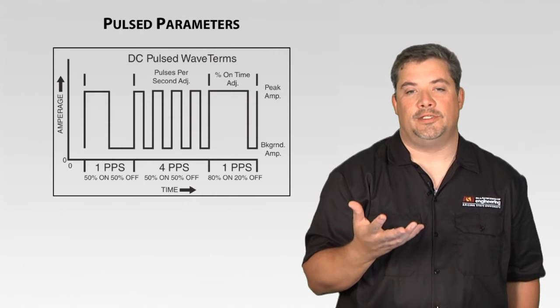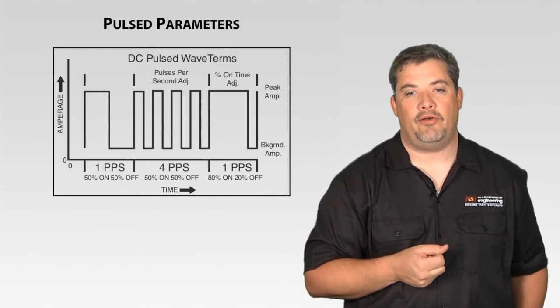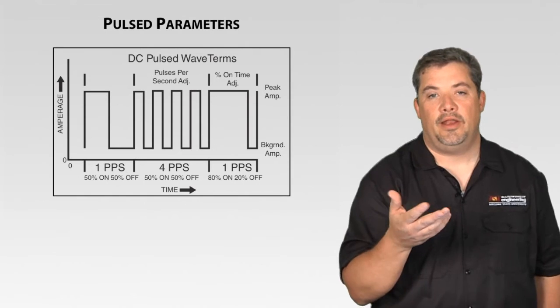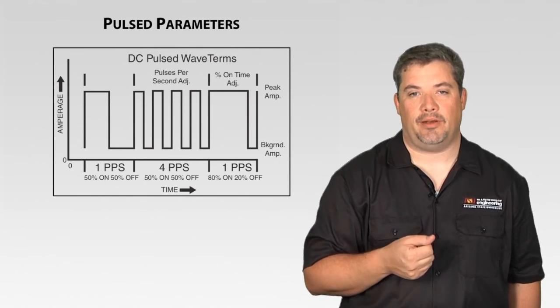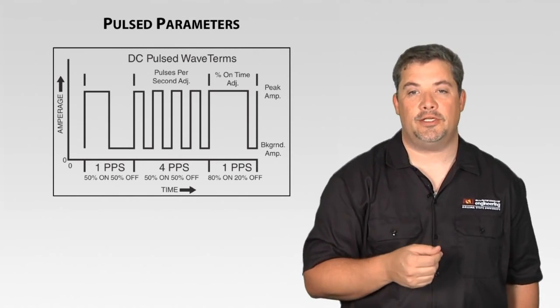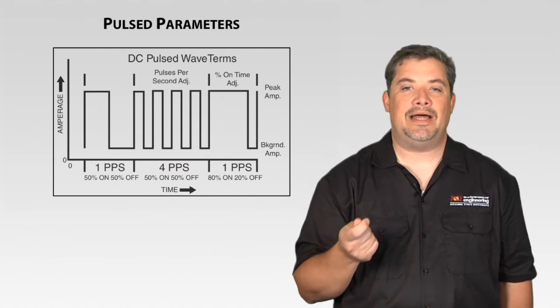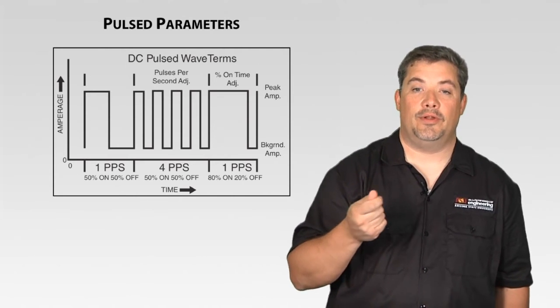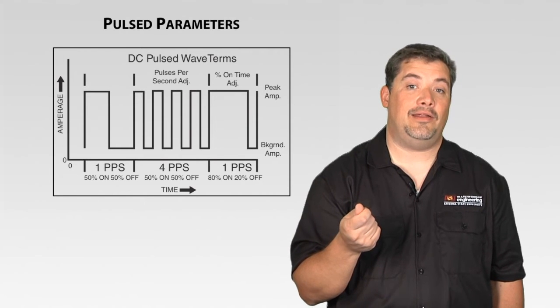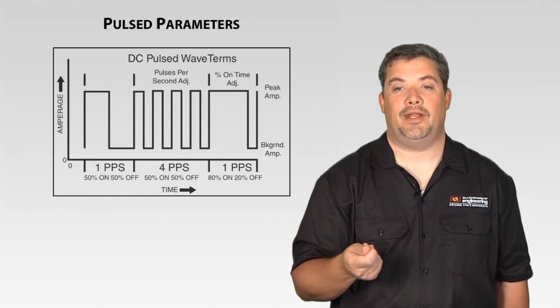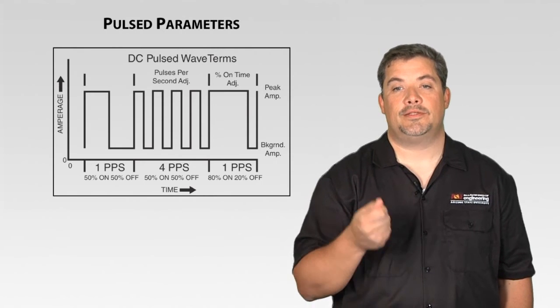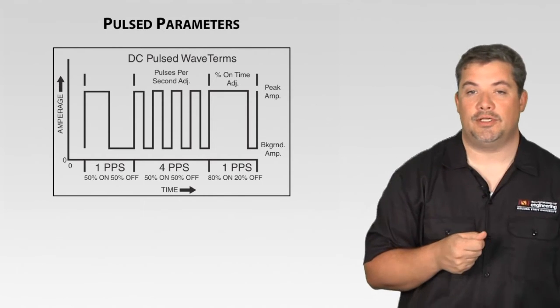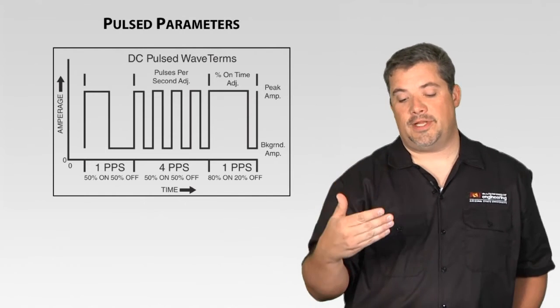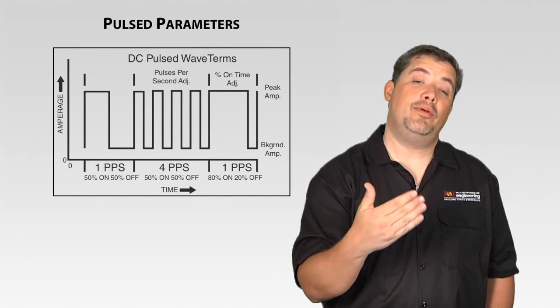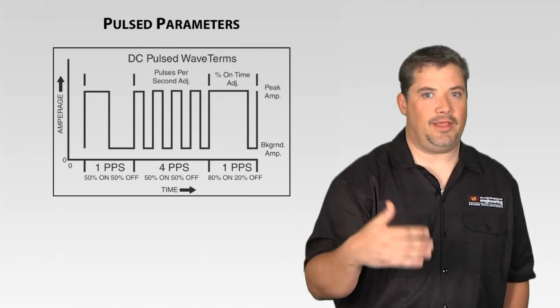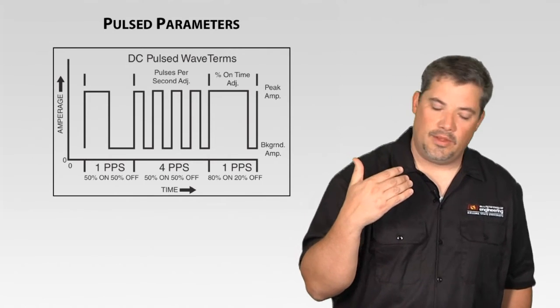So, one pulse is basically 50% on or 50% off time in these illustrations. Next to it, you can see 4 pulses per second by comparison. So you have a pulses per second adjustment. Then you have a percentage on time adjustment. So in other words, 80% of that cycle time, it's on the peak current level. So then 20%, it's on the background amperage level. So there's a peak amperage and a background amperage that you adjust as well. So understanding what you're adjusting and having that repeatability to find those spots significantly controls how your weld is affected.